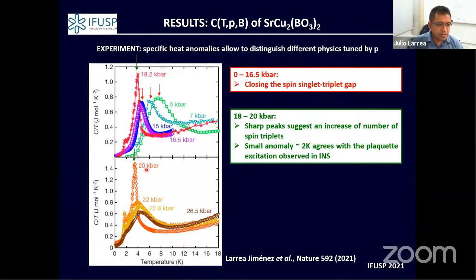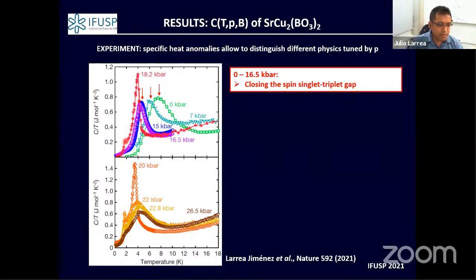Another thing you can see is that at 20 kilobar the sharp peak appears. Another thing you can observe is that at lower temperature, you can distinguish another anomaly.